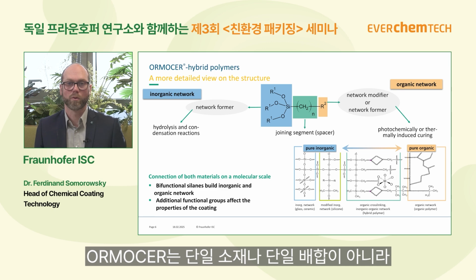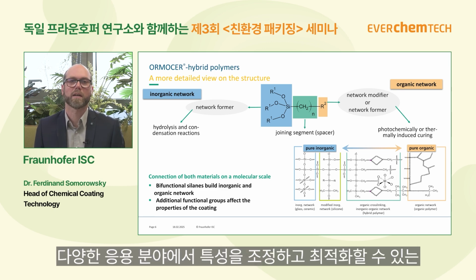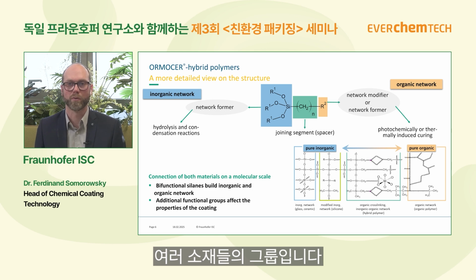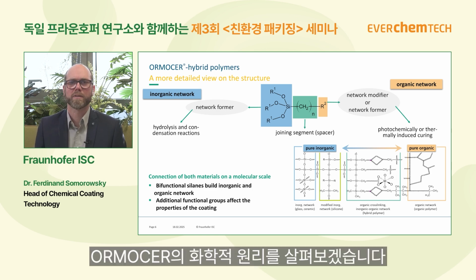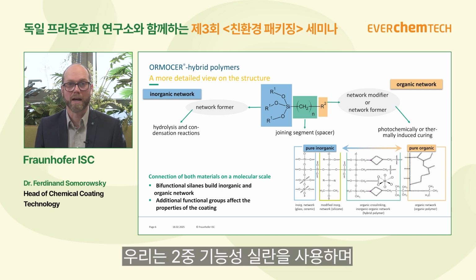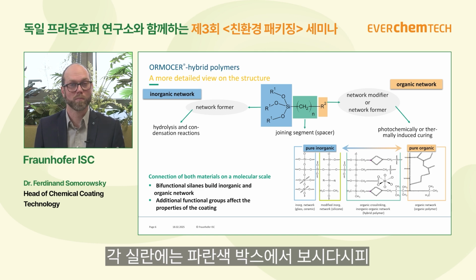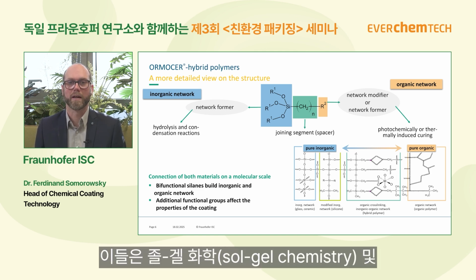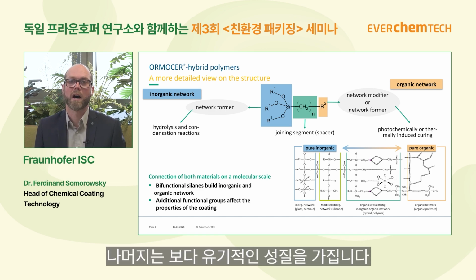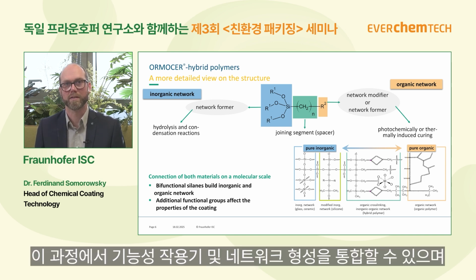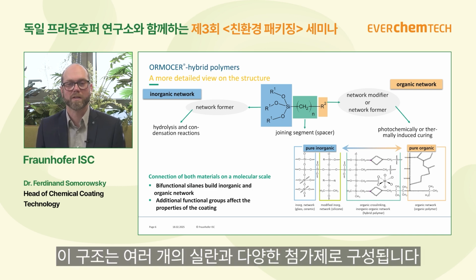So ORMOCER is not one material, one formulation, it's really more like a material class with the potential to adjust and optimize the properties in a huge range of materials. What is ORMOCER itself? A little bit of the chemistry: we use bifunctional silanes. All of the silanes have this blue box, the siloxane groups, and they will be processed by sol-gel chemistry, so hydrolysis and condensation, and the other parts are more organic. So here we can integrate functional groups, also network formers, and ORMOCER consists of several of these silanes and then also other additives.